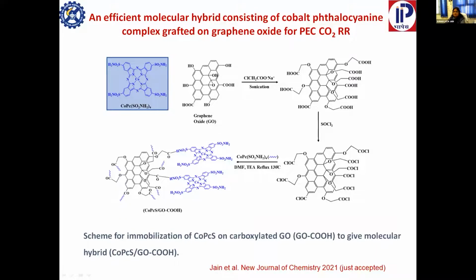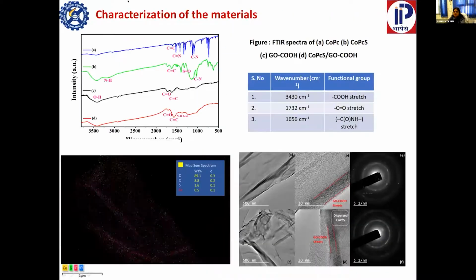Some of the systems which we have recently developed, like the cobalt phthalocyanine complexes grafted on graphene oxide. So this is the graphene oxide, this is cobalt phthalocyanine. For increasing the oxygen functionalities, we functionalize this support and then immobilize this covalently. This is the covalently immobilized system. That system was analyzed and characterized by several techniques, and we successfully synthesized and characterized it.